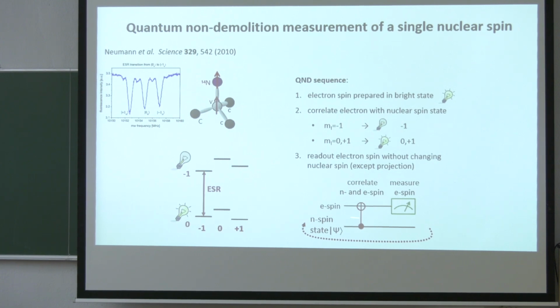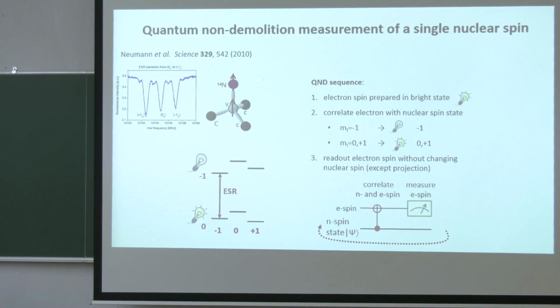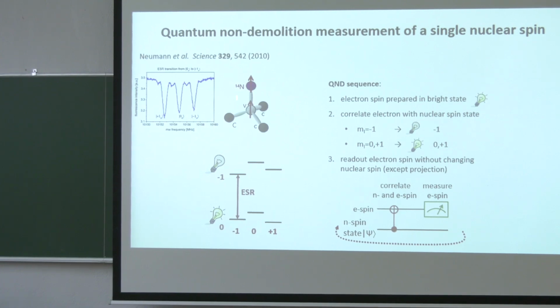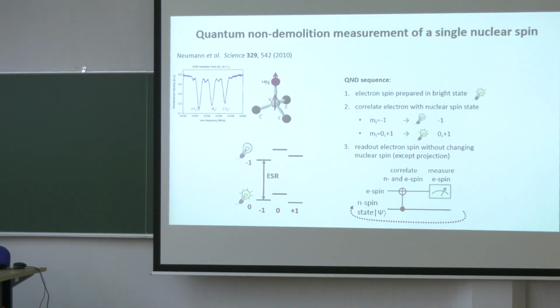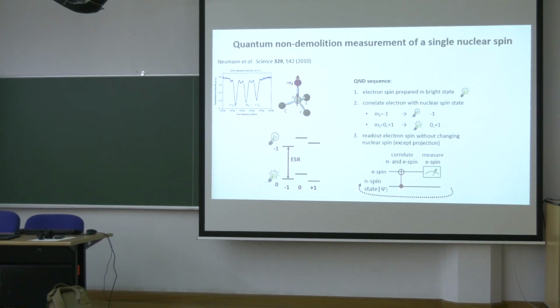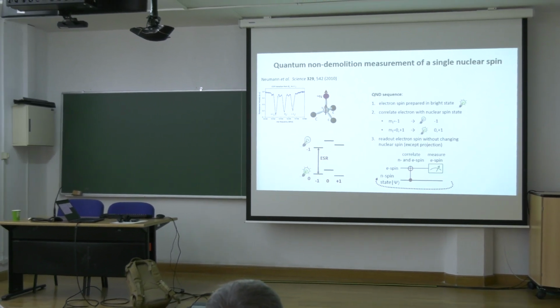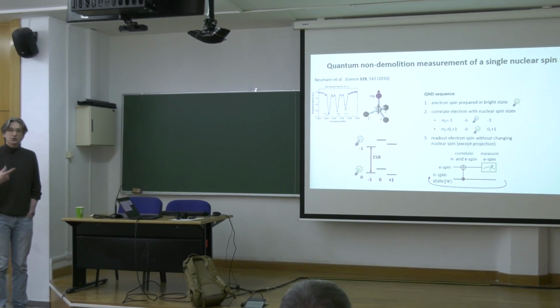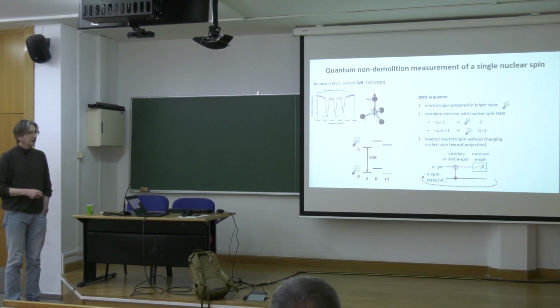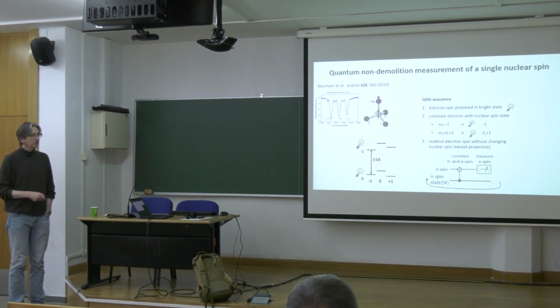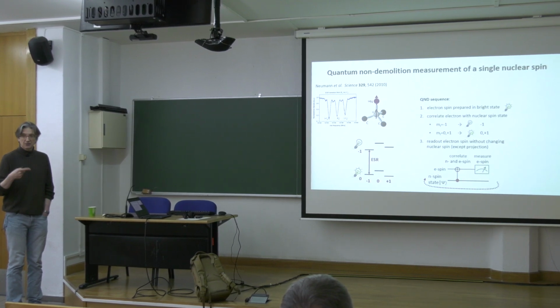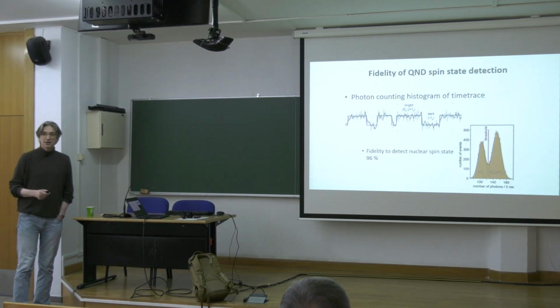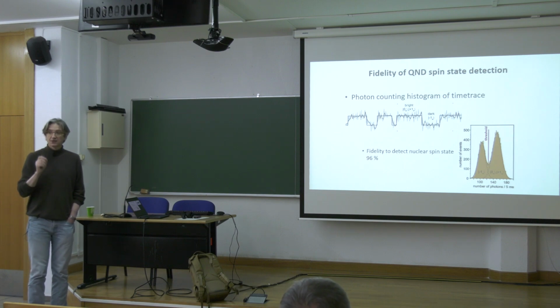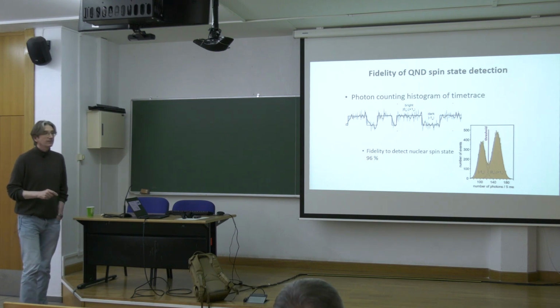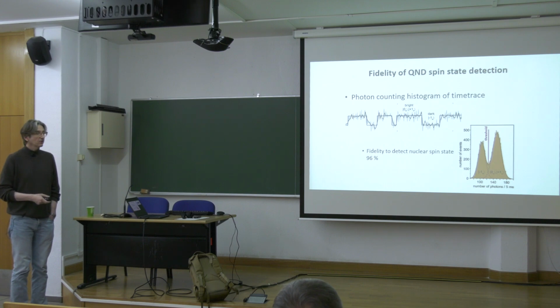And in principle, you can also map the state of the nuclear spin to the state of the electron spin and then measure it optically by using quantum gate type operations. If you do this, you can get access to the nuclear spin state of the color center. So basically, making a swap operation between electron spin and nuclear spin, and then measuring the electron spin, you can repeat it many, many times. In this case, you can observe dynamics of a single nuclear spin. And because of longer coherence time and longer relaxation time, that allows you to observe quantum jumps.